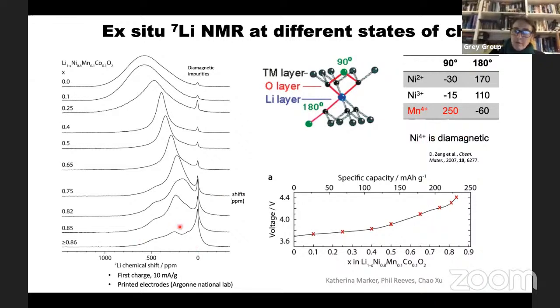And so when you're at top of charge, all you see are the manganese ions, and the manganese 4 plus is D3, so T2G3, and that has very large shifts. And what you can see is the lithium near 1 manganese and 2 manganese there. So that's just what I've just told you. But the question then is, what's going on here?